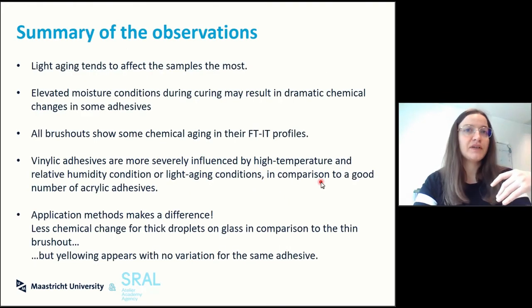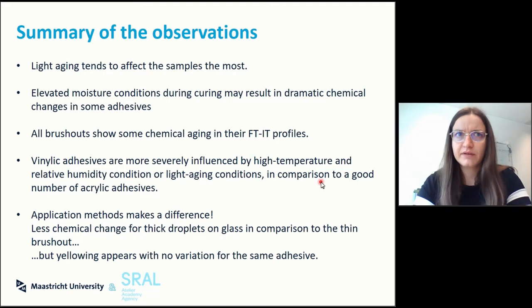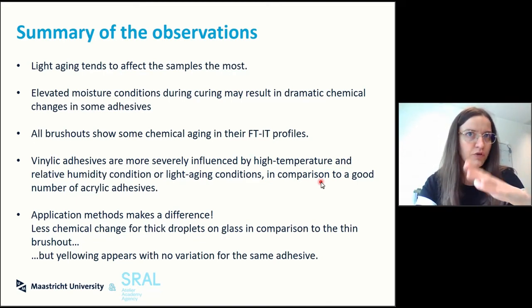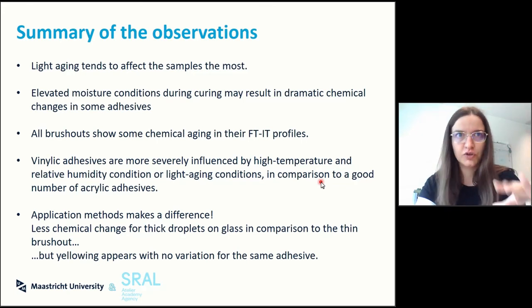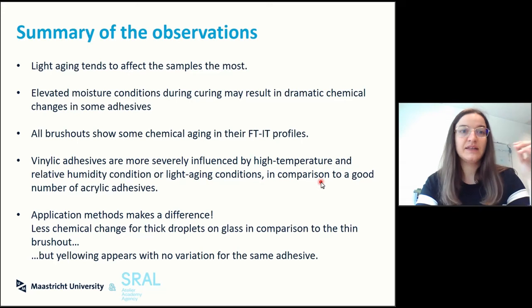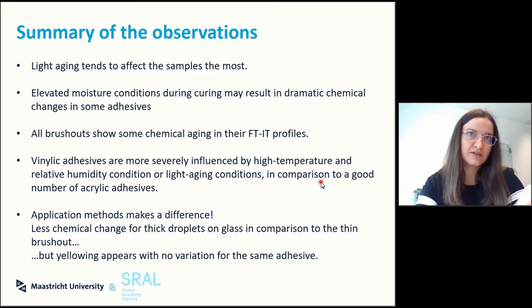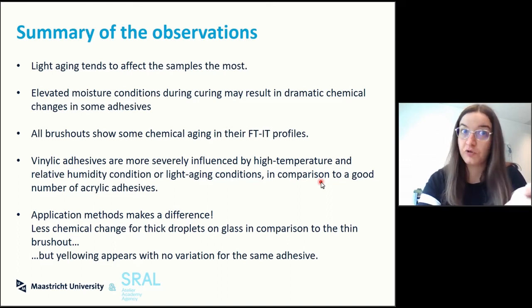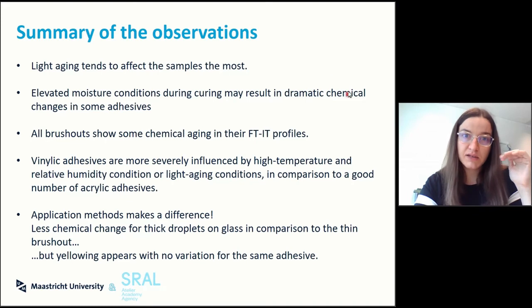And to summarize this observation, which you will find better unpacked in the papers with a division between also functional group and fingerprint region of the spectra, here we can see that the light aging in general is something that really affects your adhesives, which is not completely surprising because the photochemical issue with polymers is always true. But in some adhesives, you must be careful when using them in very high humidity and hot conditions, because the changes that we see, chemically speaking, are extreme, which will mean that your adhesive will not behave potentially like you were thinking.